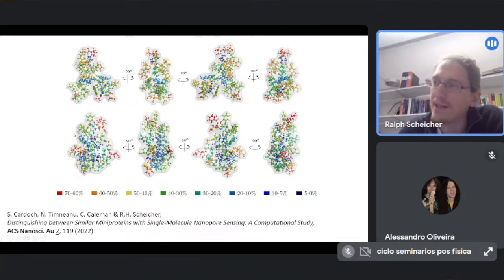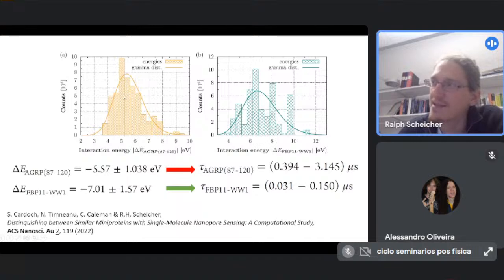And so what we've done is construct a map, basically, which says how likely it is to find an amino acid close to the surface. And taking this distribution into account, together with the interaction energies calculated from density functional theory, we then finally obtained some interaction energy for the two different mini proteins. Here for this one mini protein, here for the other.